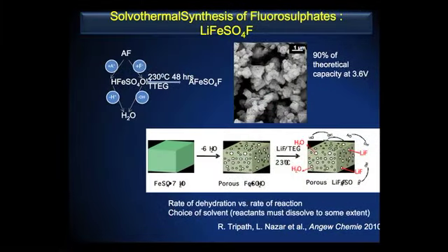So as I said, maybe these little guys are necessary. But if you're lucky, you can control the chemistry. So this just shows an example of the synthesis of a new class of materials. These are lithium fluorosulfates. And this material, you can easily get 90% of the theoretical capacity at 3.6 volts, a little higher than the olivine I just mentioned.